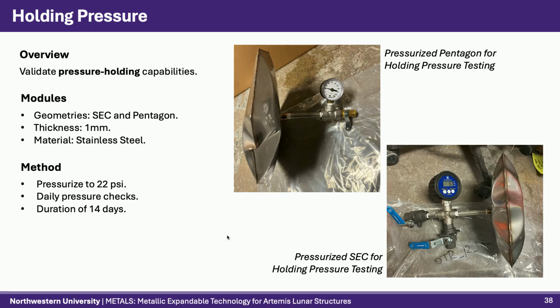To validate metals' pressure holding capability, the SEC and pentagon geometries were inflated to 22 psi and stored without manual depressurization for a 2-week period. Daily pressure checks revealed that while the SEC developed pressure leaks along the Teflon tape sealing the pressure gauge, the pentagon maintained 22 psi throughout the 14-day trial. This demonstrates that metals can effectively hold pressure when properly sealed.